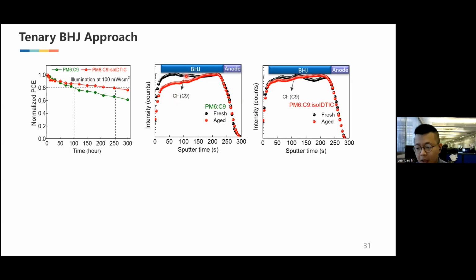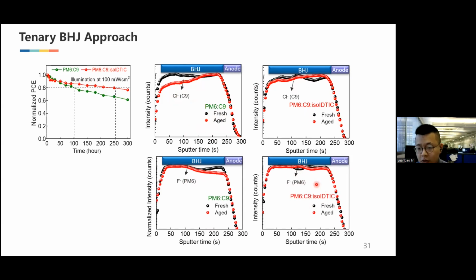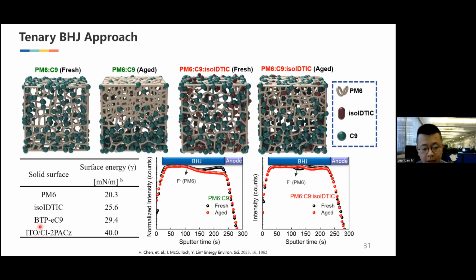We used ToF-SIMS to see the donor-acceptor distribution in the aged and fresh devices. In the binary, after the stability test, the BTP-eC9 will degrade toward the ITO side. But for the ternary, the distribution is more homogeneous compared to the binary system, and also for PM6 it is very homogeneous. This is because iso-IDTIC has a suitable surface energy, and after adding it as a third component, it can reduce the acceptor's surface energy a little bit, so it partly enhances the homogeneous distribution of donor and acceptor after the aging test.